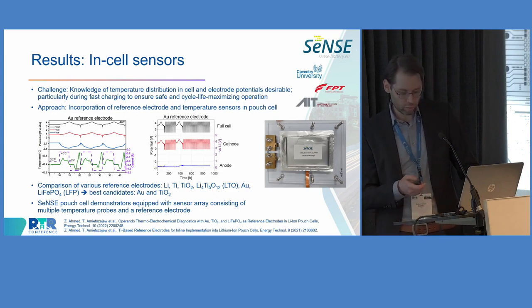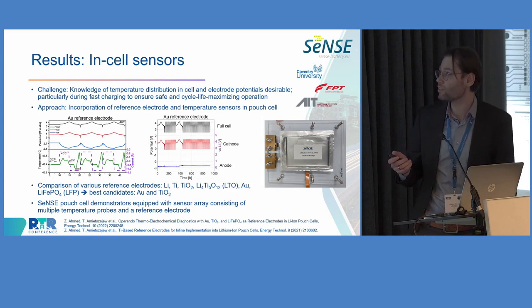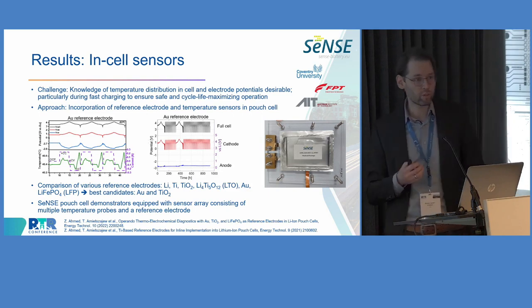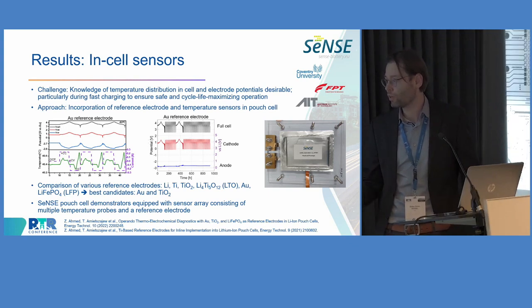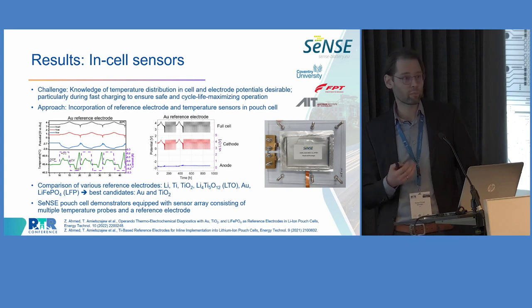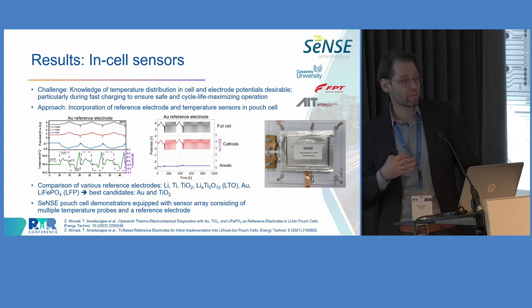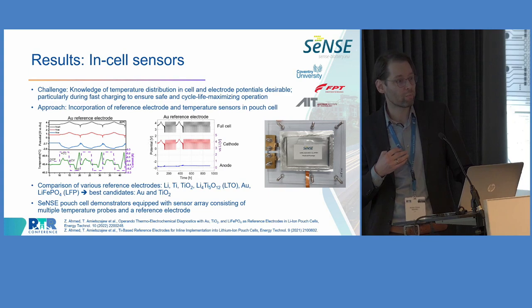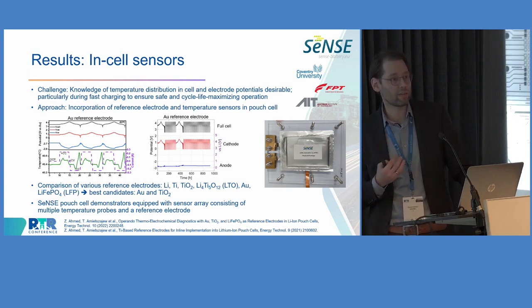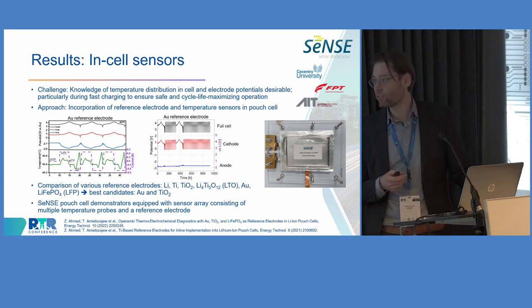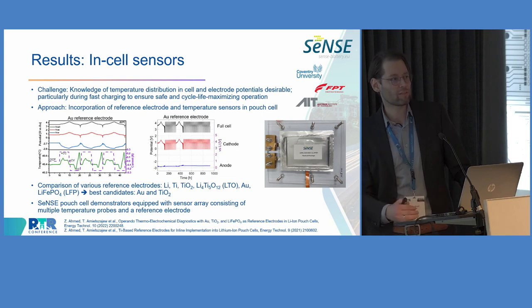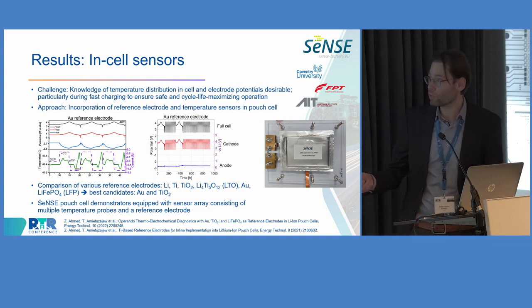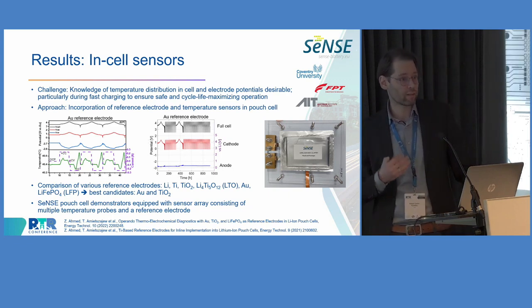The last example I would like to highlight today: I already mentioned that we're also working on in-cell sensors, and here our partner Coventry University from the UK has the lead. They published two nice papers in this project where they investigated multiple reference electrodes. We are not only interested in the temperature distribution in the cell, but also in the individual electrode potentials, which is particularly important to learn more about the state of health of the silicon-based anode, and also for fast charging, because we want to avoid states of the cell where it comes to lithium plating. Lithium plating means that the potential of the anode drops below the lithium plating potential, and that's the state you want to avoid.